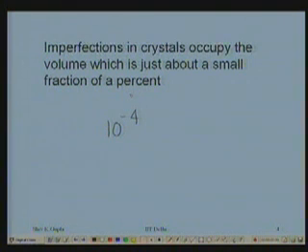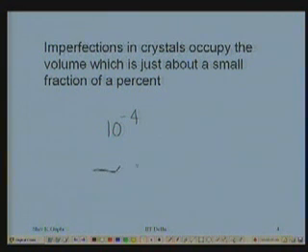So, in other words, what I am trying to say is the fraction of a percent of a particular imperfection, or fractional volume occupied by an imperfection, is very small. At room temperature, I might have a fraction of the order of 10 to the power minus 17. That is 1 out of 10 to the power 17 is the volume which is defective or an imperfection. So, it is a very small volume which we are talking about.